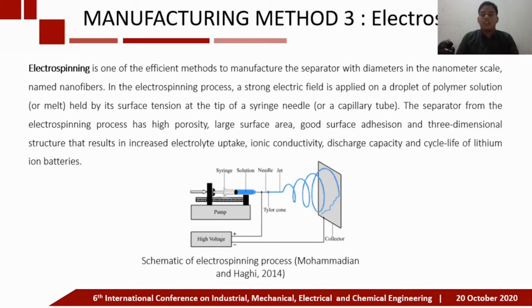The third method is electrospinning. Electrospinning is one of the efficient methods to manufacture the separator with diameter in the nanometer scale, named nanofibers. In the electrospinning process, a strong electric field is applied on a droplet, a polymer solution or melt held by its surface tension at the tip of a syringe needle or a capillary tube. The separator from the electrospinning process has high porosity, large surface area, good surface adhesion, and three-dimensional structure that result in increased electrolyte uptake, ionic conductivity, discharge capacity, and cycle life of lithium-ion batteries. We can see in the picture that this is a schematic of electrospinning process.